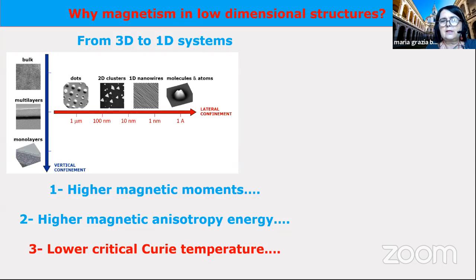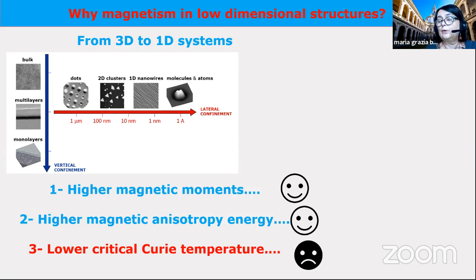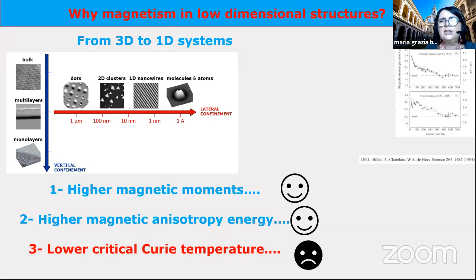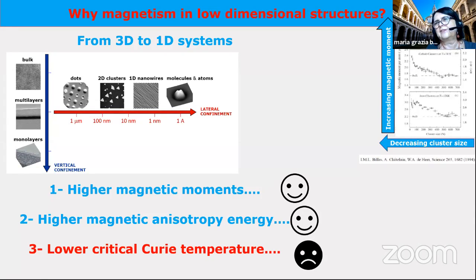Then there are two added values. Then there is also a lower critical Curie temperature if you reduce the size. So the first two are positive. The third one is negative because at room temperature, maybe you can destroy your magnetic state. There has been a lot of research in the last, I can say, 40 years on these systems, and this on the right is a very nice Stern-Gerlach experiment to demonstrate that you have a higher magnetic moment if you decrease the cluster size.